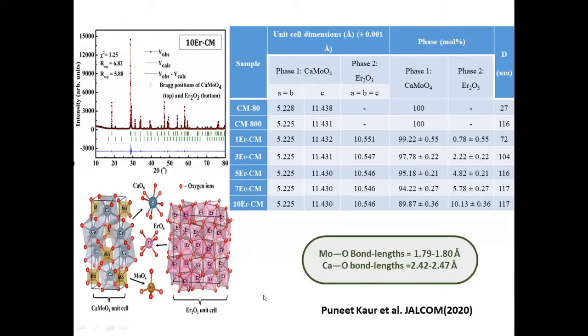the erbium ions. So the erbium ions, they exist in the octahedral geometry. Each erbium ion is surrounded by 6 oxygen ions. Molybdenum has tetrahedral geometry, whereas each calcium ion is surrounded by 8 oxygen ions. So you can do modeling of the structure of the material, and the molybdenum oxygen bond length is 1.8 angstrom, and calcium oxygen bond length is in this range of 2.42 to 2.47 angstrom.